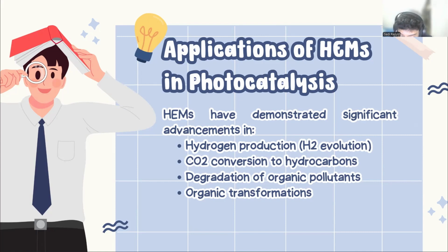Lee investigated the organic photocatalytic conversion strategy of hydrothermally synthesized HEO nanoparticles. HEO were fabricated by hydrothermal method, and due to the abundant active sites and synergistic effect of multiple metals, the HEO catalyst exhibit significant activity in oxidative coupling reaction and benzimidazole cyclization reaction. The yield of the two target products reached 88% and 91% with selectivities of 99% and 98% respectively.